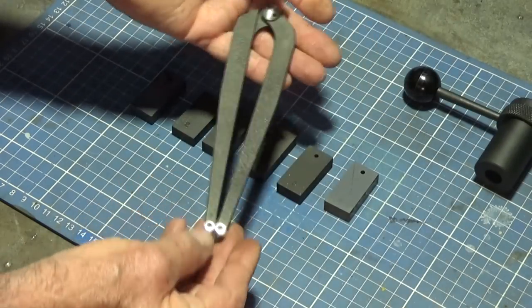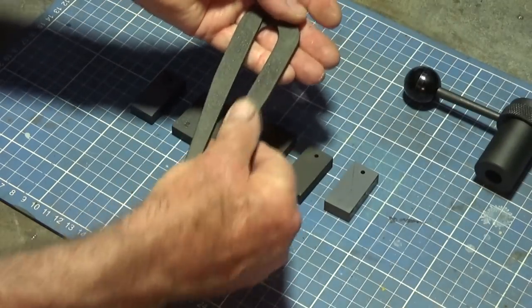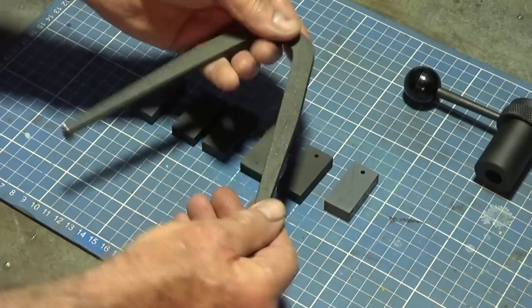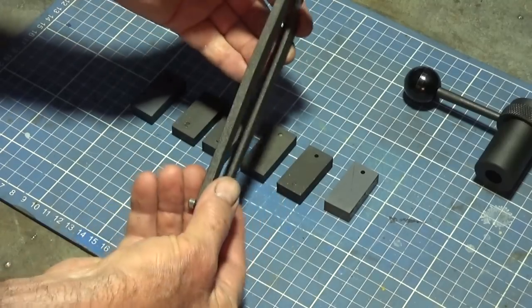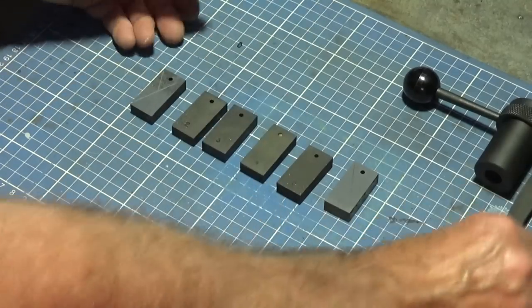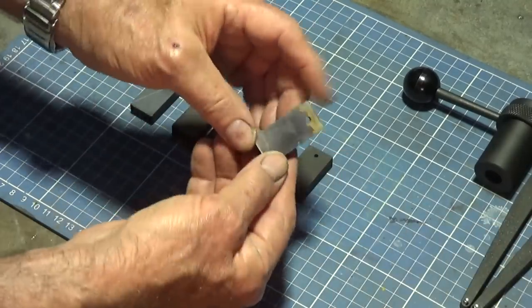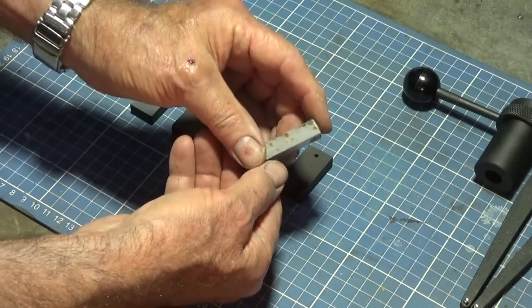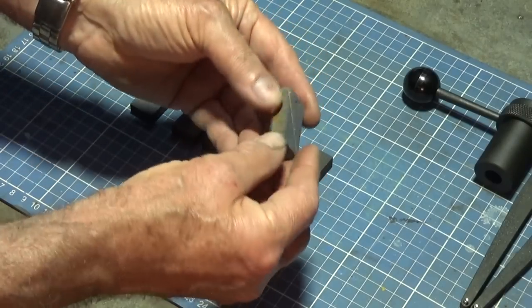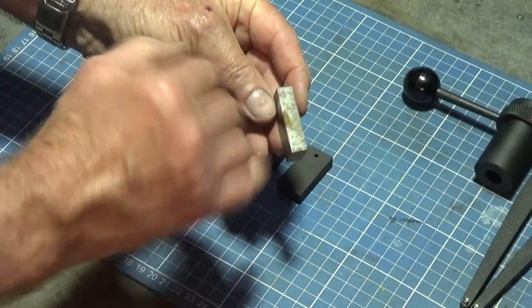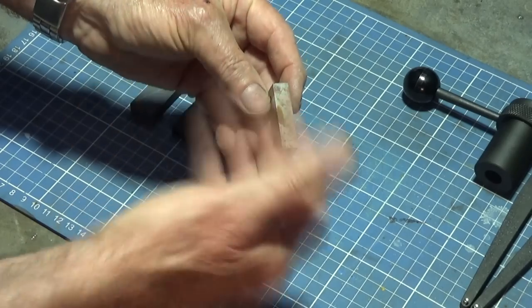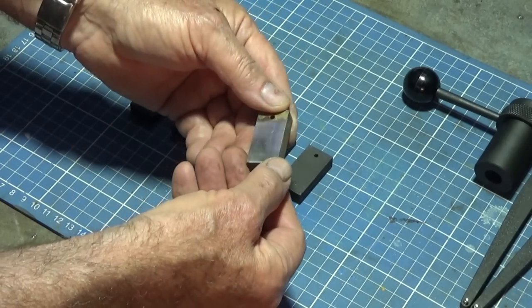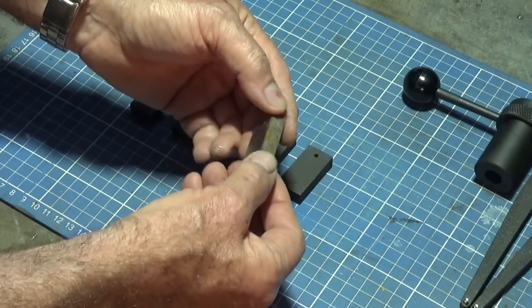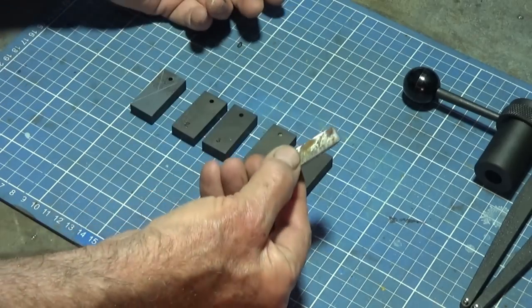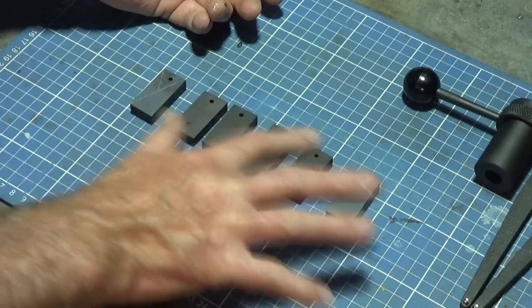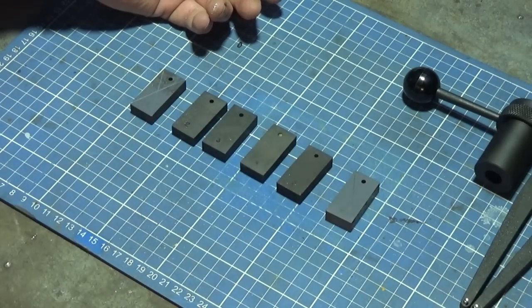This is the other one. This has been sitting in a drawer though. It still feels slightly oily. And once again, absolutely no sign of corrosion anywhere on that. This one, the bare steel, clearly the corrosion has started and it'll only get worse. Once that oxide coating gets going, it absorbs more moisture and that accelerates the process. So bare steel, even if it's polished, even if it's oiled, is not going to last as well as I think this Parkerised coating is going to.